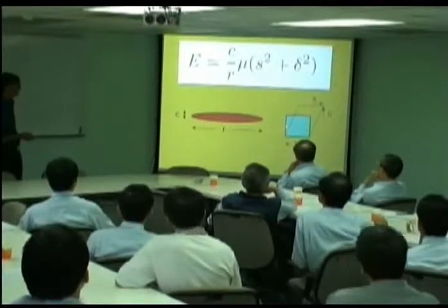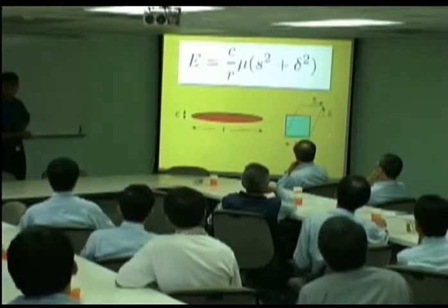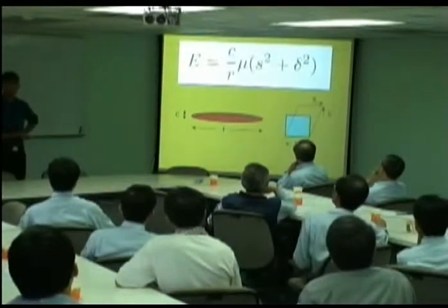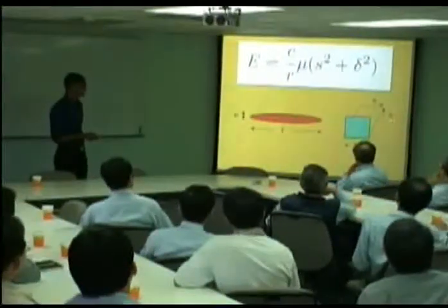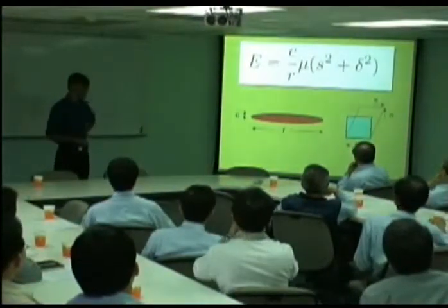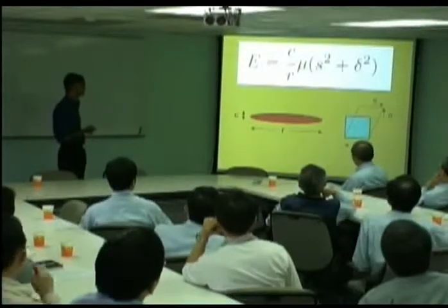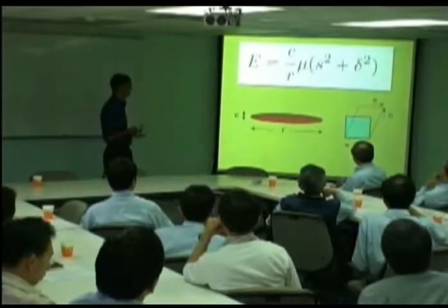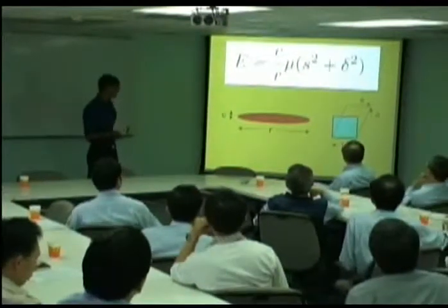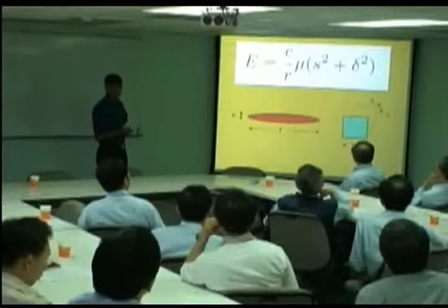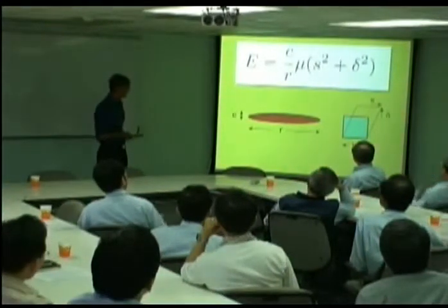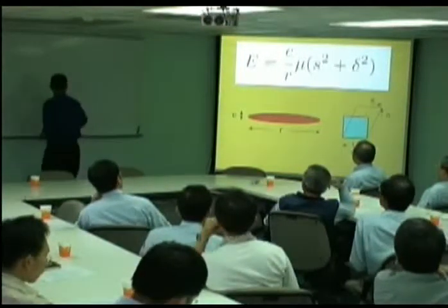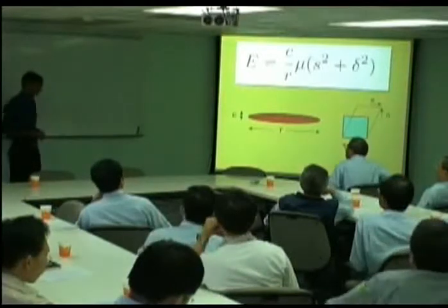Now, the reason why it's a plate shape is very straightforward. If you work out the elastic strain energy per unit volume because of the shape change, and this is a shear deformation of about 0.26, and this is a volume change of about 0.03, then the elastic strain energy per unit volume is related to the shear strain, the volume change, the shear modulus of the austenite, and the thickness over the length. So obviously, this is minimum when we have a plate shape.